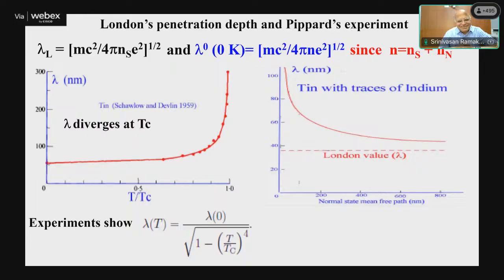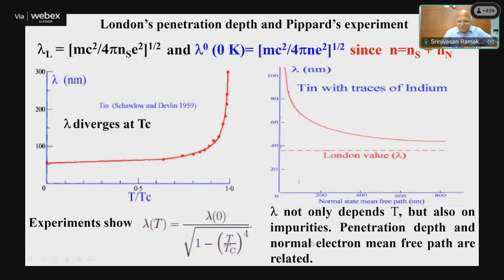But Pippard didn't do that. In those days, the number of people working in the superconductivity area was quite small. So Pippard decided to give an explanation by simple intuition. So lambda not only depends on T but also on impurities. The penetration depth and the normal electron mean free path are related, because when you put indium in tin, the mean free path of the tin will decrease as you put more and more indium into the system.